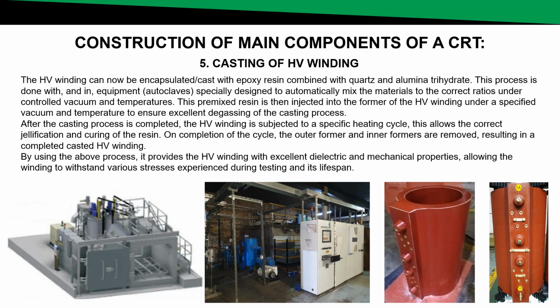This allows the correct gelification and curing of the resin. So should you also not follow the prescribed heating cycle, you will also find that the resin will either cure too quickly or too slowly, compromising the insulation and later the PD testing of that high voltage winding. Once the heating cycle has been completed, the outer and inner formers or jackets can now be removed, resulting in a complete casted HV winding.